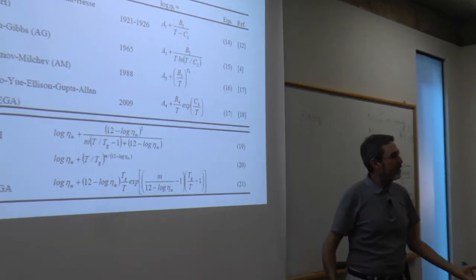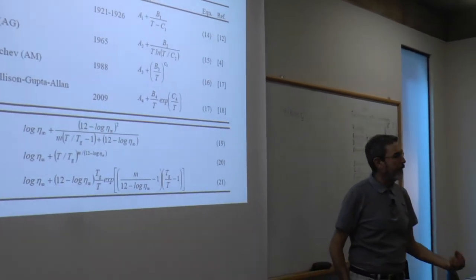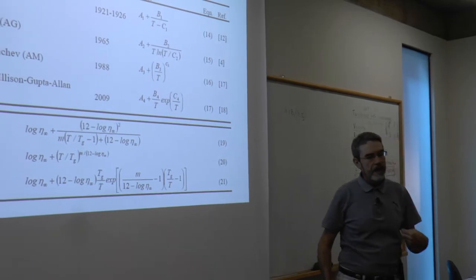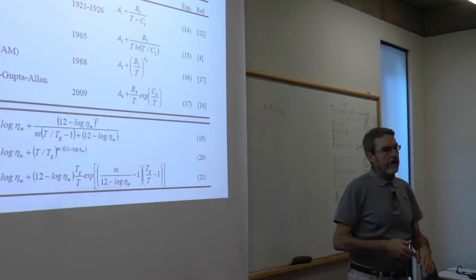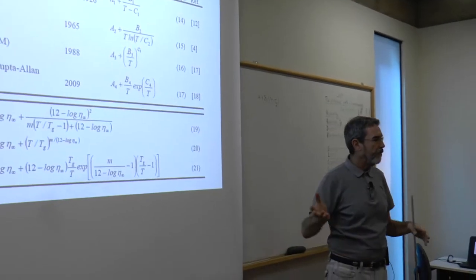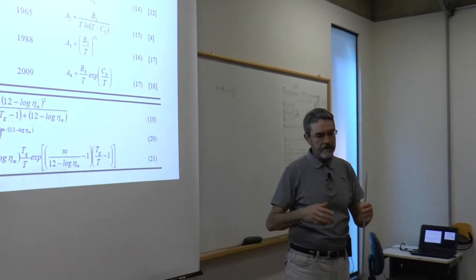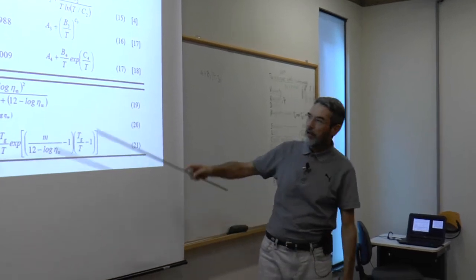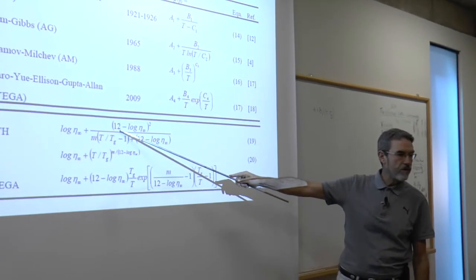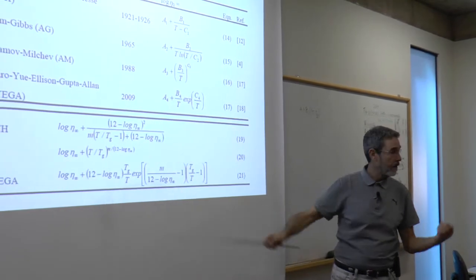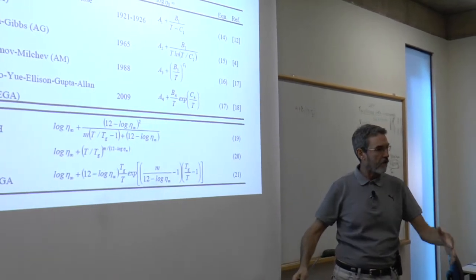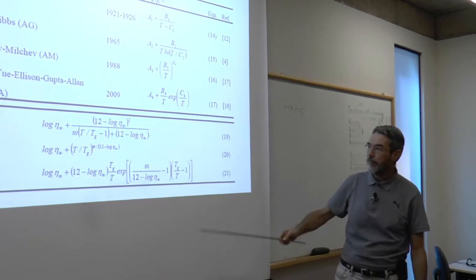Tg is the glass transition temperature of the glass. And to normalize this temperature for different heating rates, cooling rates, etc., the value of 12 is used. The log of viscosity is 12. So this is the meaning of this 12 here. It's the log of viscosity at Tg.